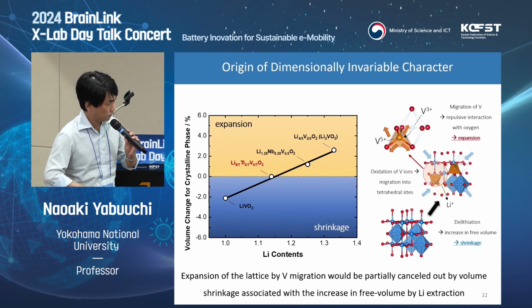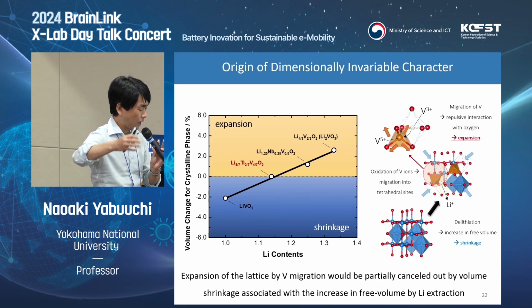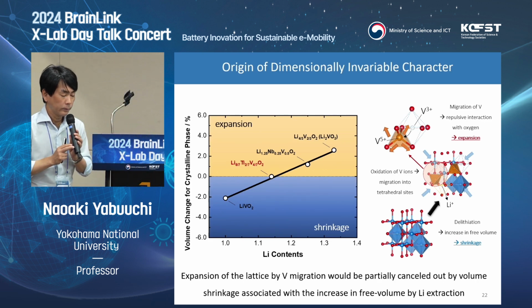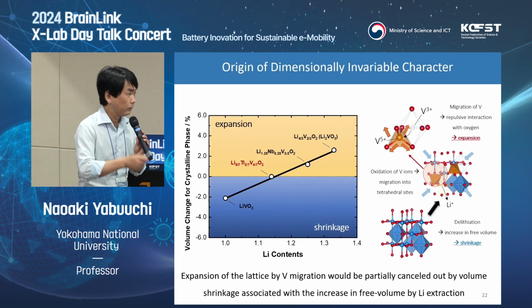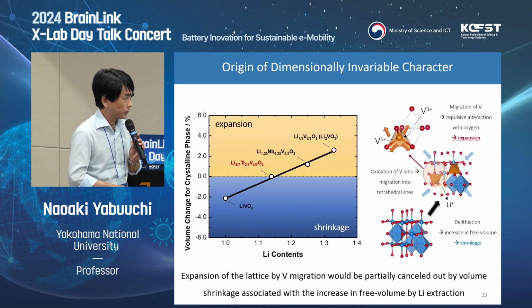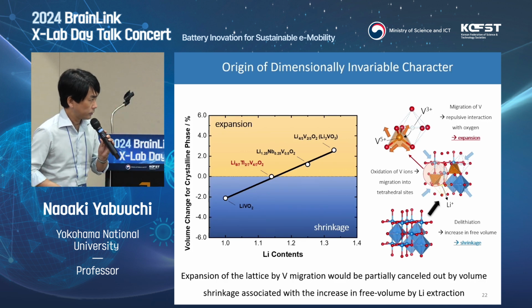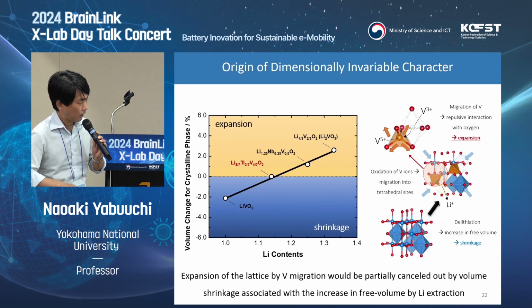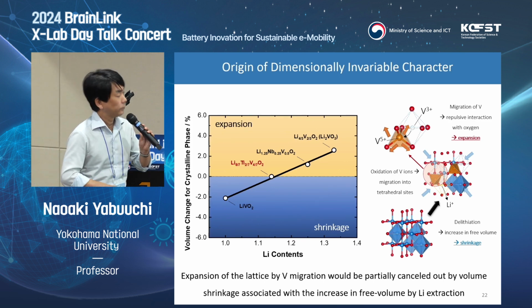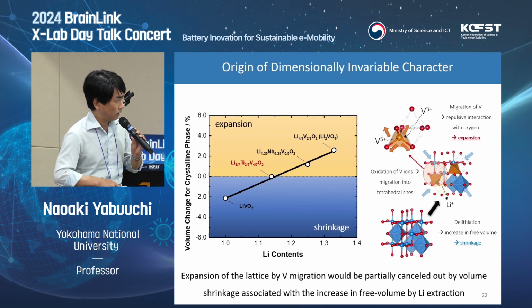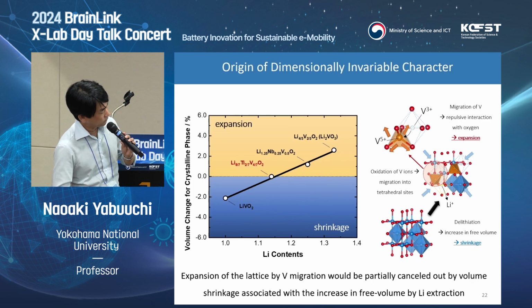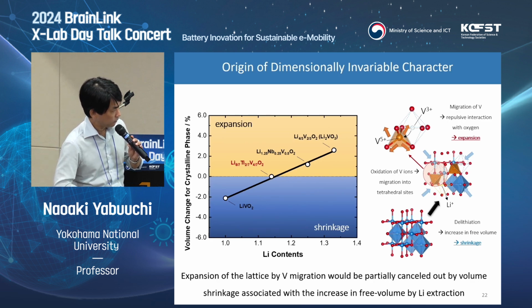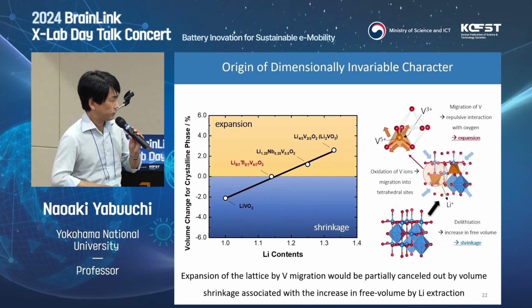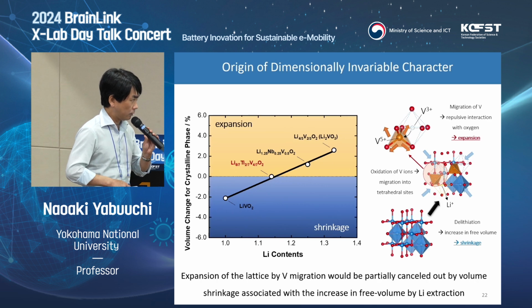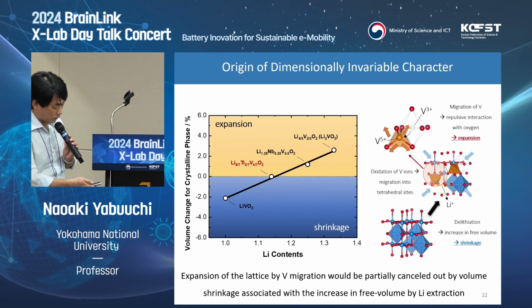Increasing lithium contents means you have more oxygen, and the ionic bonding nature is increased. When you compare the thermal expansion for more ionic compounds and covalent compounds, for example, diamond, a typical covalent material, shows a very small thermal expansion. This is also the same: as increasing lithium contents means a more ionic bonding nature, similar to thermal expansion, the volume change upon charging is also increased. And our materials are found here, with a moderate amount of lithium contents. So we can design zero volume change materials by optimizing the chemical composition and also the vanadium ion contents.